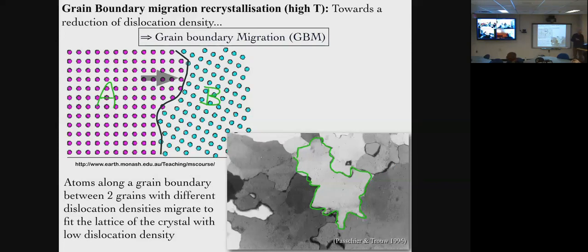Good question, okay? So in this particular process, diffusion becomes activated also. That's the other difference, right? In bulging, which is at lower temperature, it is mostly dislocation. Here, the atoms are in fact changing their bond attachment from one crystal that's highly disorganized, breaking that bond, reattaching themselves to a more organized, dislocation-free grain, okay?